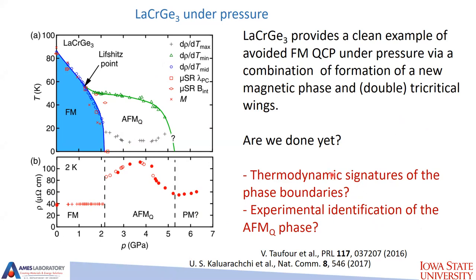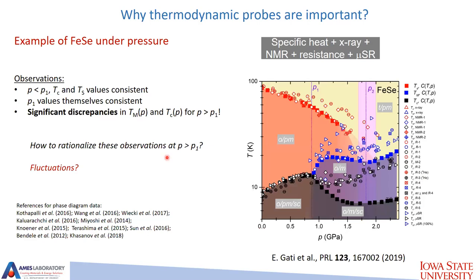Now, why are thermodynamic signatures important? In many good, well-behaving materials, it doesn't matter what you measure, transport, thermodynamics, whatever, you will have the same phase lines. Some features are more clear in one measurement or another, but there is no discrepancy. However, sometimes, as an example of iron selenide, there is a profound difference. I will not go into it, you can read this paper.